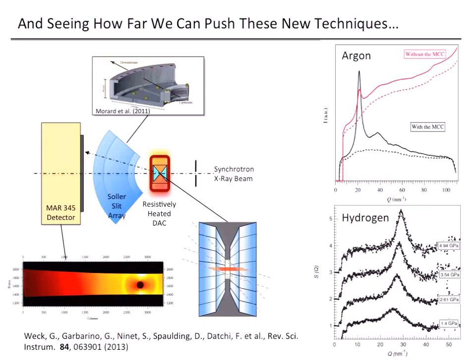And what these slits do is they basically serve as sort of a spatial filter to limit the diffracting volume that the detector sees. So we couple this with the resistively heated diamond cell so that we can look at coordination changes in these low Z molecular fluids and step up in pressure and temperature in the fluid state and look at how that coordination changes.